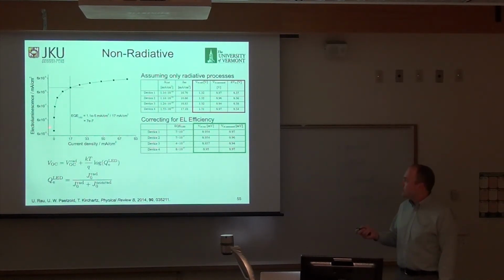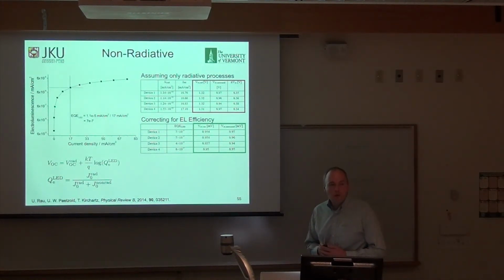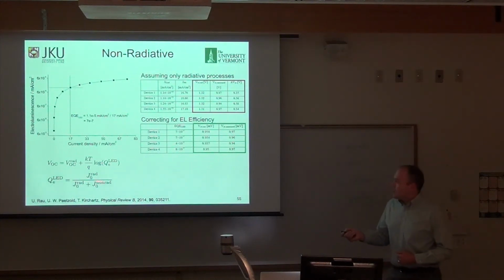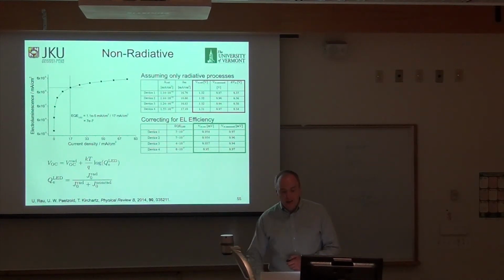What we did was we operated all of the solar cells as LEDs and measured the quantum efficiency of the LED, the electroluminescence quantum efficiency. We plugged that into this equation that was specified by Rau here. Our prediction based off of this analysis comes out to be exactly what we measured. If you assume that there's only radiative recombination, you have left unaccounted for this 300 or 400 millivolt loss. But it can all be accounted for by this loss in the luminescence, which is present in both photoluminescence and electroluminescence. So this is a real problem if we're going to use this electrode.